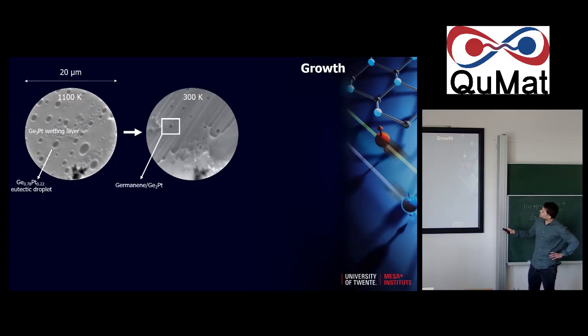But if you look at such an image, you also see some elongated structures over here. We understand these little dark spots, but at the beginning we didn't understand where they were coming from. Sometimes they were in the experiment, other times they were not there. There was quite a bit of inconsistency between one experiment and the other. So the question that we have is, what are these elongated structures?